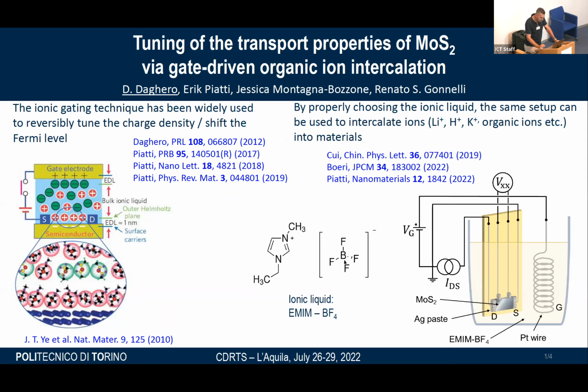For example, by using this kind of ionic liquid, which is called EMIM-BF4, it is possible to induce the intercalation with hydrogen. And this is what we did in a single crystal of MoS2. And this is the setup. So this is the ionic liquid. This is the counter electrode, which is actually the gate. We apply the potential difference and we measure the resistivity of the sample while applying the gate voltage.